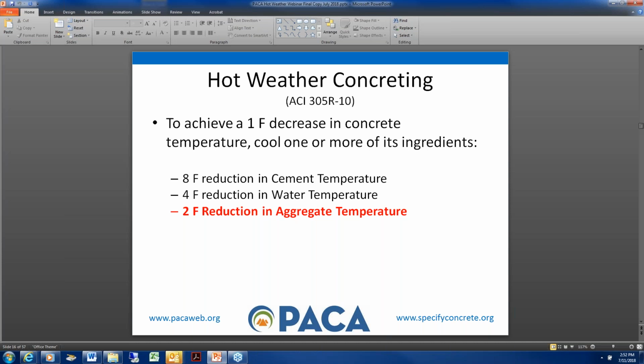Yeah, you can actually maybe even get a touch more if you put them all in concert, I think. I always like to be conservative assuming that. Yes, I will, Rob. I'll tell everybody listening, if you have a second water chiller, if you can run chilled water on your coarse aggregate, you can see a 10 to 15 degree reduction in your coarse aggregate temperature real quick. Huge, huge difference.